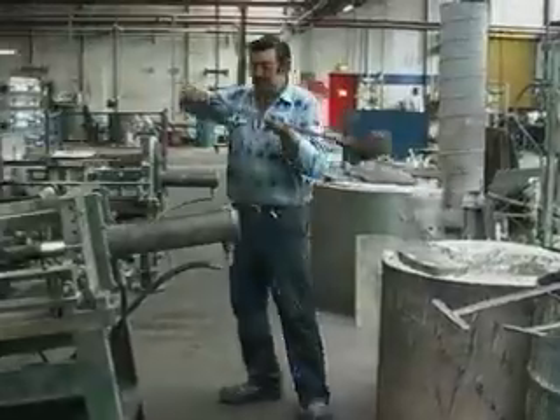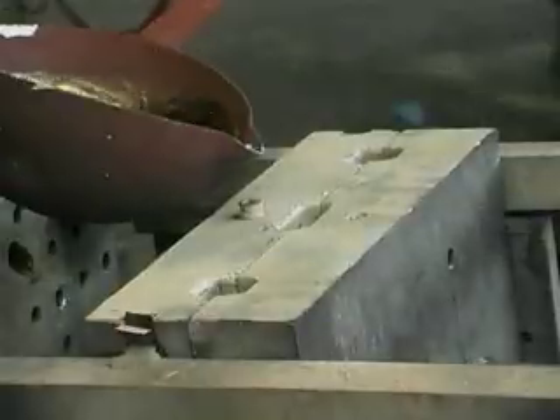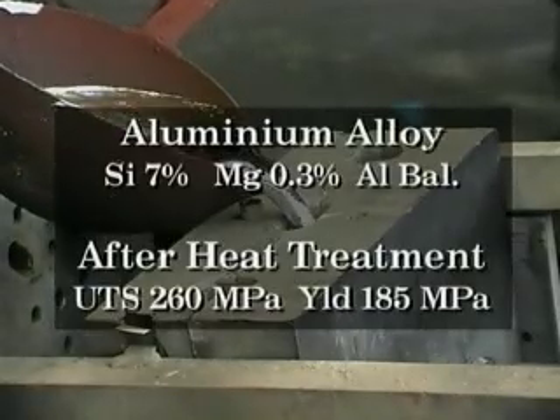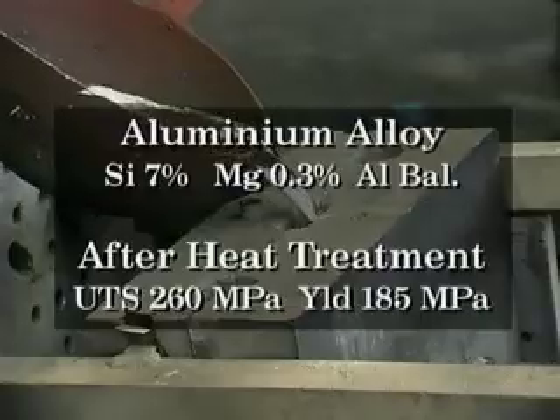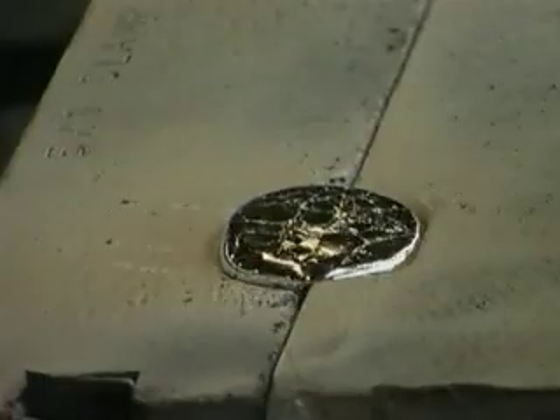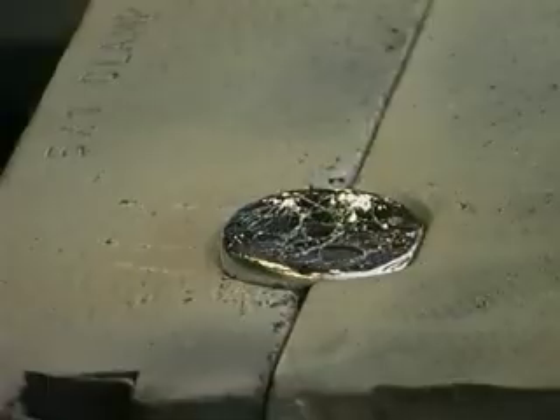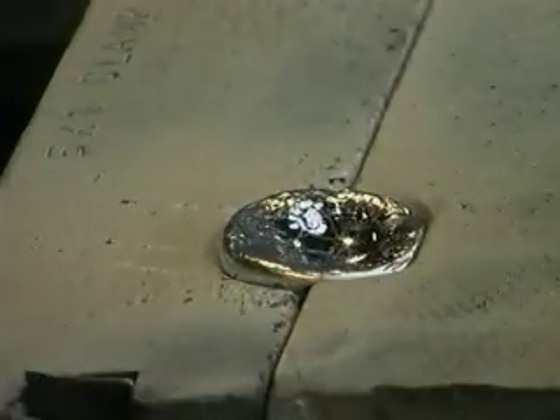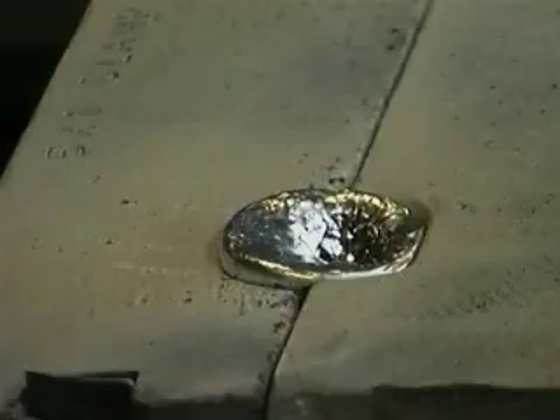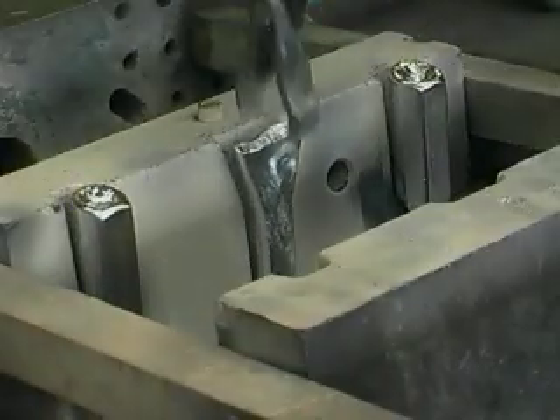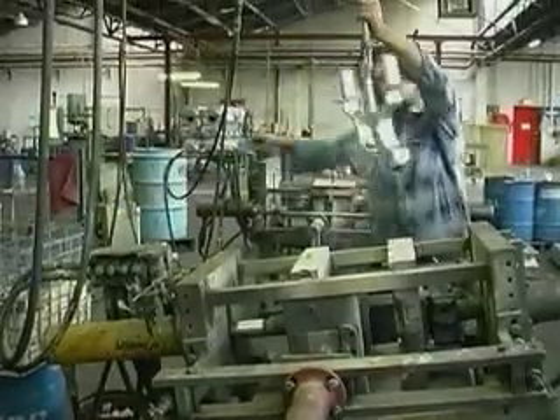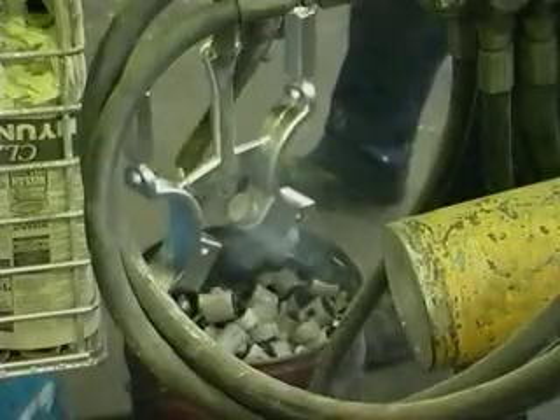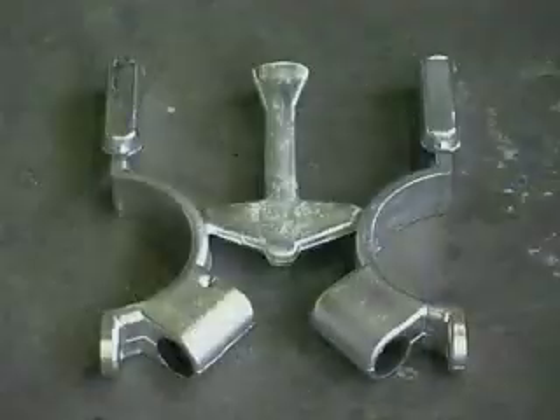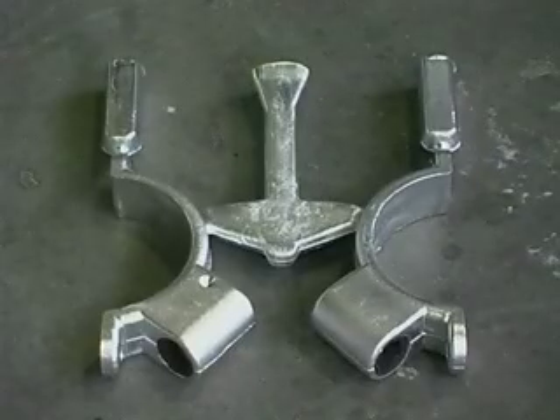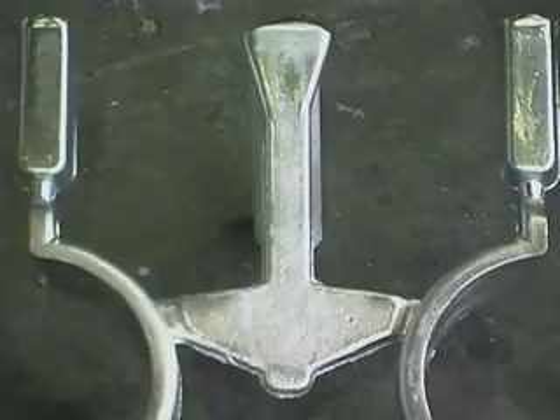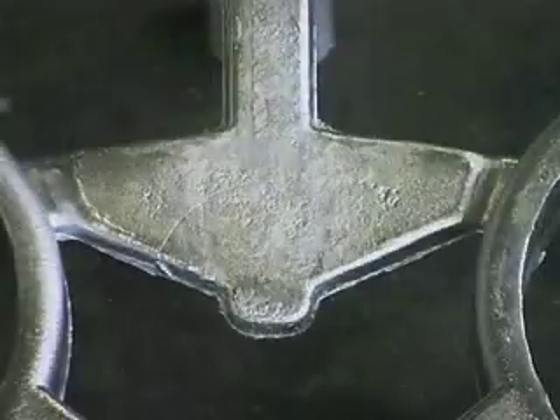The most commonly used alloy in gravity die casting is the aluminium silicon magnesium alloy, as it has good castability and good mechanical properties. The metal generally takes 1 to 4 minutes to solidify. These risers feed the casting with molten metal. Ceramic die coats are sprayed onto the die, and these will help control the rate of heat transfer within the die. Components suitable for gravity die casting will generally have wall thicknesses greater than 3 millimeters, and commonly weigh between 200 grams and 10 kilograms, although much larger castings are possible.